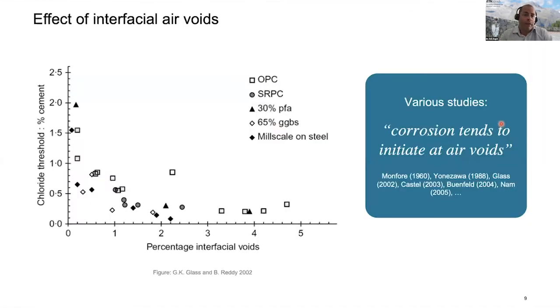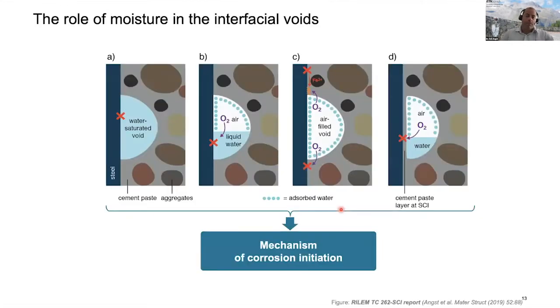Now, moving on to the effect of interfacial air voids, there is a lot of literature that indicated that corrosion in concrete tends to initiate preferably at interfacial air voids. And there is one very famous, well-known figure in the literature, which was produced by Glass and Reddy in the year 2002, which shows that with an increasing amount of interfacial air voids, the chloride threshold value decreases. Now, one particular aspect of all these studies is that they were performed at a relatively high degree of pore saturation of the porous matrix that surrounds the steel. And when we look at conditions where we have a lower degree of saturation, we actually observe a slightly different case. And that brought us in this RILEM technical committee to the following hypothesis on the role of moisture in triggering corrosion of steel in concrete in the presence of chlorides.